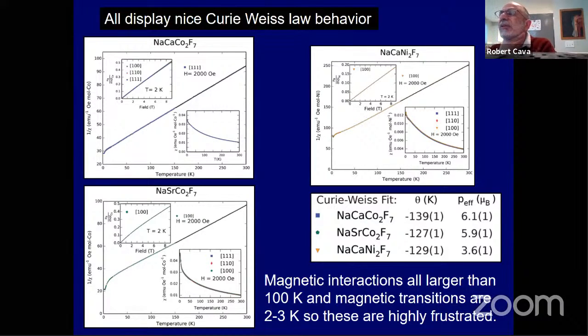So these fluorides are kind of exactly what the doctor ordered. They have interaction temperatures of 100 Kelvin now with big magnetic moments. You grow giant crystals in the floating zone furnace, and you can then study frustration on a pyrochlore lattice at a humanly accessible temperature, which is a few Kelvin, not a few millikelvin.